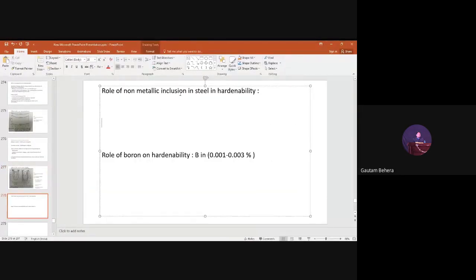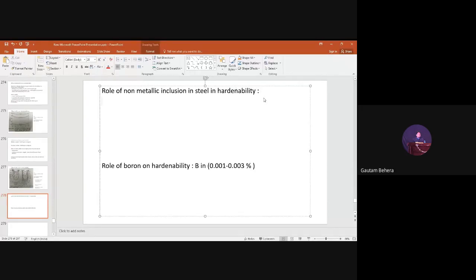Okay, last part, the role of non-metallic inclusions in steel on hardenability. Non-metallic inclusions, if you remember, may be oxides, or sulfides, or silicates, or complex oxides like that. They basically prevent the coarsening of the grain, so the grain will remain finer. If we have very fine non-metallic inclusions, below 10 micrometer or 10 micron, and there is a uniform distribution of these oxides, sulfides, silicates, or complex oxides, there is a refinement in the grain size. And if the grain size is smaller, hardenability will be poor. You can answer poor hardenability.